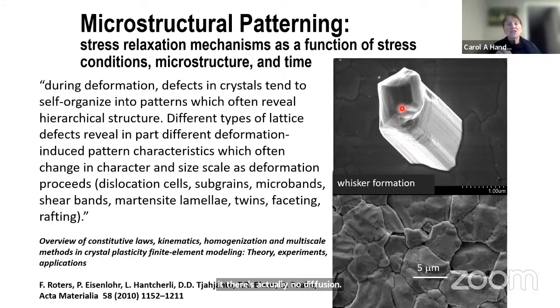So this actually memorializes, it retains all of the structure and processes that happen. So this grain was originally flat on the surface. It actually showed whisker formation, but only in part of the grain. So it tilts up. The grain boundary also migrated out. Then it migrates in, and then it migrated out.